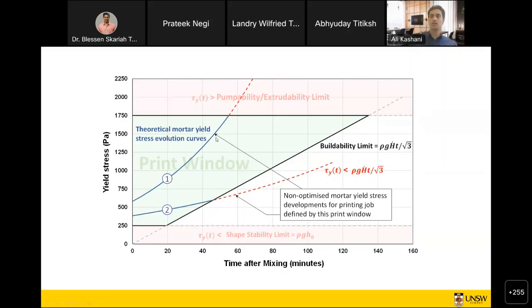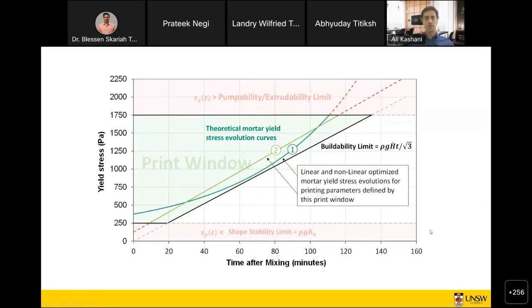So if its strength is developing too fast, it's going to pass the limit of the buildability, pumpability. And if it's developing very slowly in terms of the strength and yield stress, then the material would not be buildable. So we want something theoretically that just goes parallel to the buildability limit, starting with a good shape and stability. Even if not that, we can wait a little bit until the material gets some good strength to be buildable. So that's fine. But the main concern is about the buildability and also pumpability.